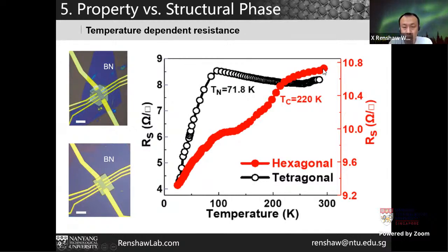And the red curve is the resistance versus temperature for the hexagonal phase. If you check carefully, there's maybe a turning point at around 220 K, which is the Curie temperature of the ferromagnetism in the hexagonal phase. If you think this is not very convincing, now I'm going to present the resistance as a function of the magnetic field to confirm the magnetic property of these materials from a different perspective.